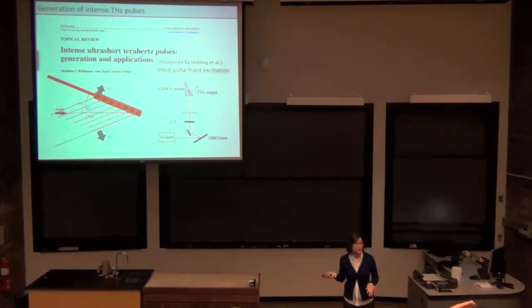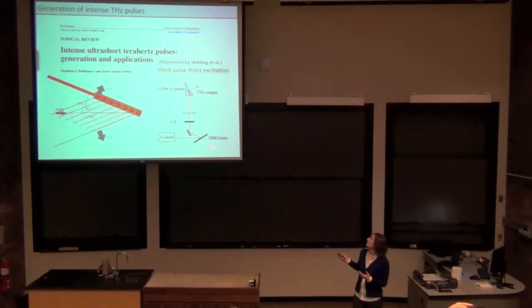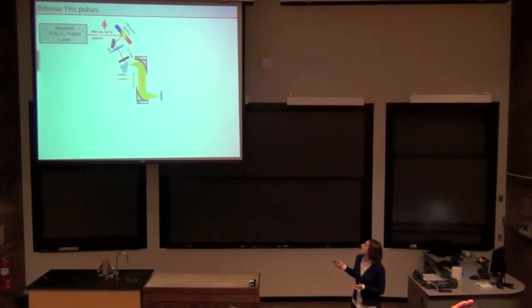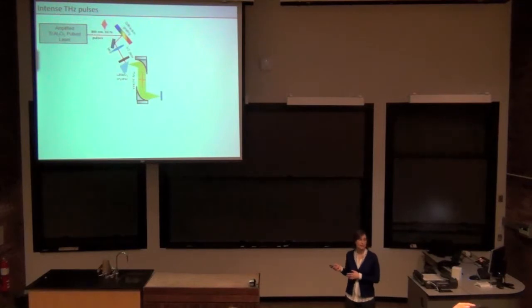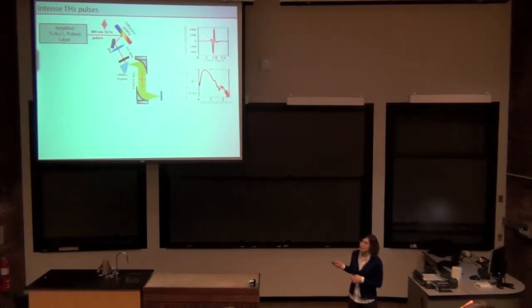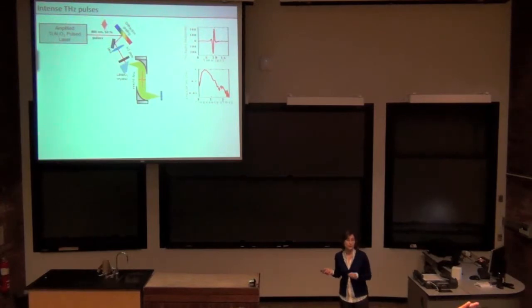How do we tilt this optical pulse front? Well, we use a grating to do that. That's the simplest way to tilt the pulse front, is to use an optical grating. This is a very simplified diagram of the setup that we use right now, and we have successfully generated 1 microjoule terahertz pulses using this setup.